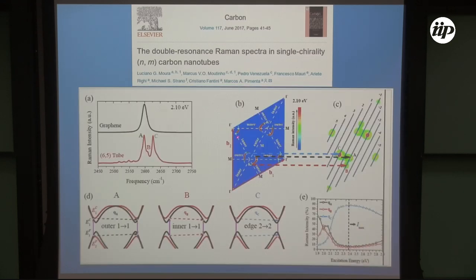So this figure here is the Brillouin zone in graphene. In a carbon nanotube, the Brillouin zone is composed of those lines because now you have a one-dimensional system. So for instance, if you have in graphene this laser energy, you measure these phonons with q vectors in this red region here. But in the carbon nanotube with the same energy, for instance, this is for the 6,5 carbon nanotube, you only see the parts of this region that belong to the Brillouin zone of the nanotube. So you don't see all these parts.